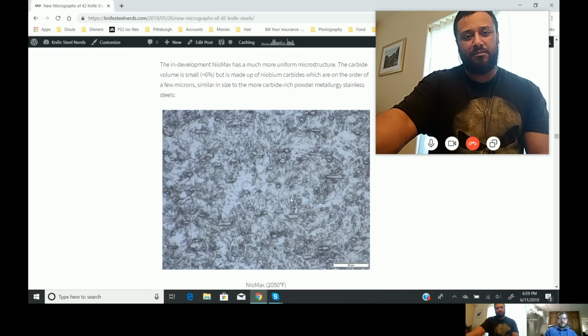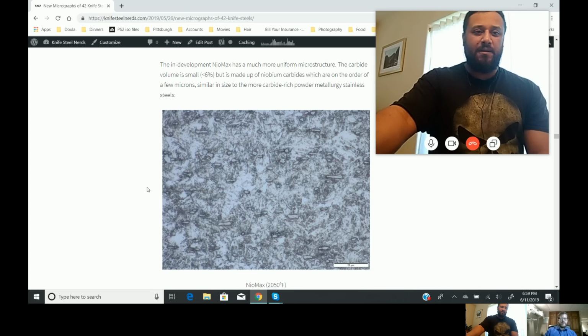So it has similar carbide size to maybe like a CPM 154, but with less carbide, and it is niobium carbide. So very hard carbides, a small volume of them, so that it offers high toughness with kind of average wear resistance, as opposed to AEB-L with good toughness but bad wear resistance.